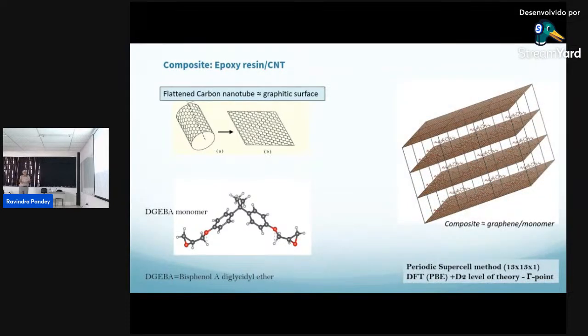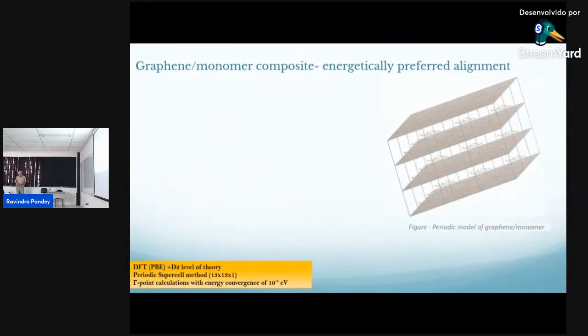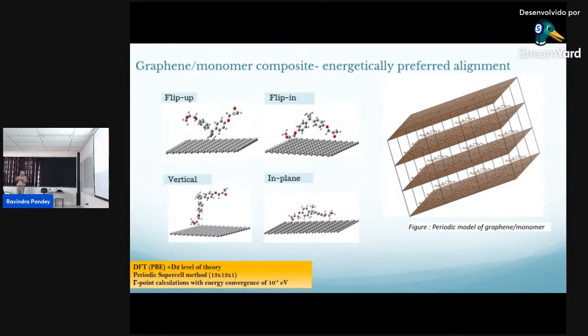And then you have this periodic supercell model where our composite is simply a graphene interacting with these monomers. And that's again what I call ground zero. A very, very approximate model before you move to a very complicated model. And then what you do is take these molecules and do a different orientation to get the total energy. So we have this so-called flip-up configuration, flip-in, vertical and in plane.